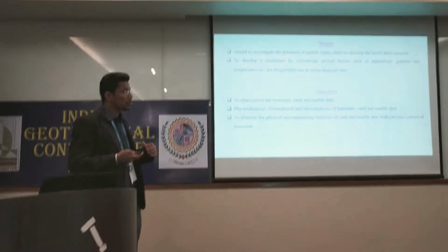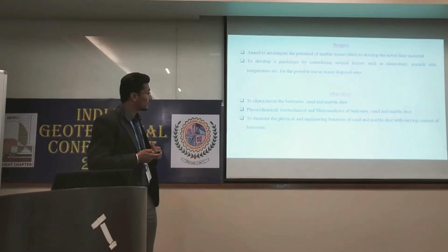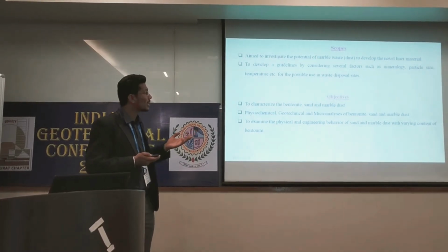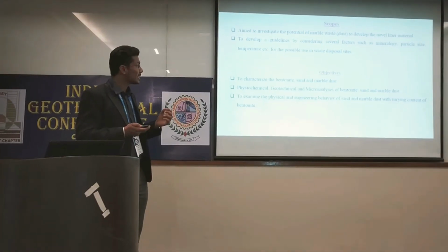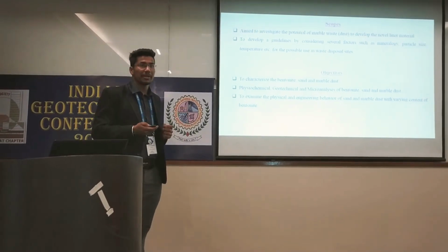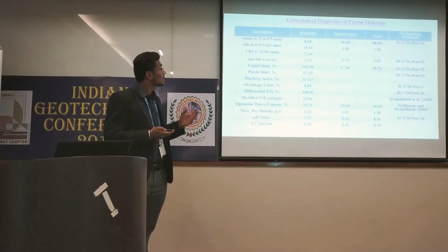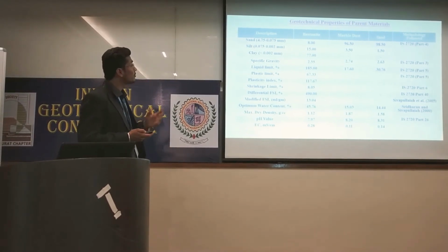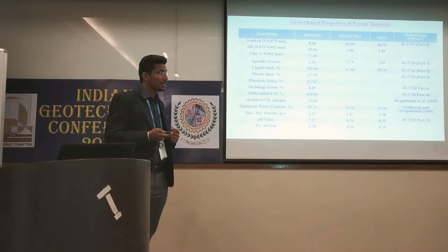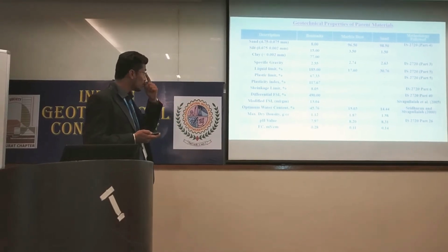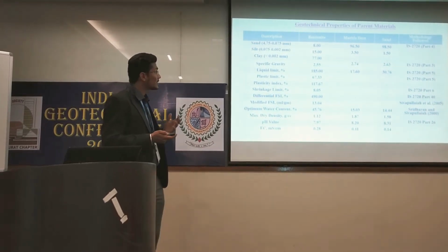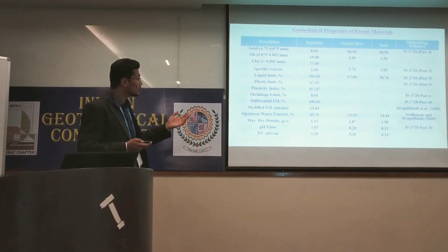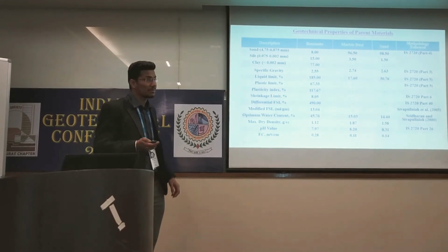This is the objective which I am going to find out: the characterization of the bentonite, sand and marble dust, after that the physicochemical, geochemical and microanalysis, further the examination of the physical and engineering behavior of sand bentonite and marble dust bentonite mixes. This is the geotechnical properties of the parent material, which shows that the liquid limit of bentonite is much higher than the marble dust and sand, as well as the swelling of the bentonite is very high as compared to marble dust and sand, as well as the maximum dry density is also very low as compared to the sand and marble dust.